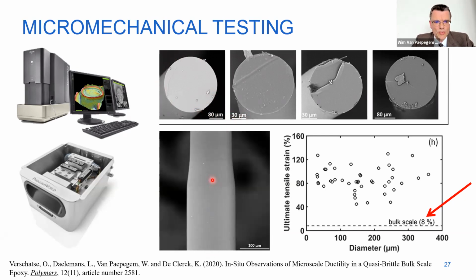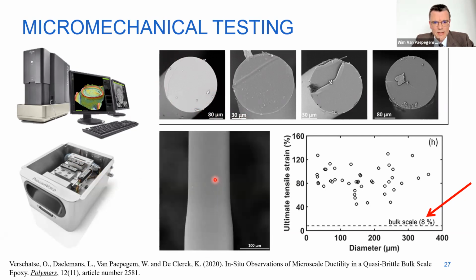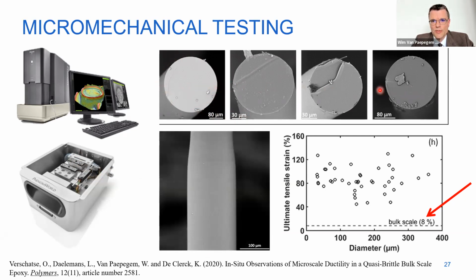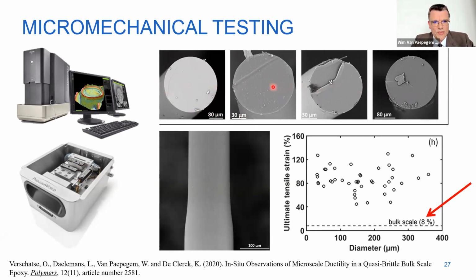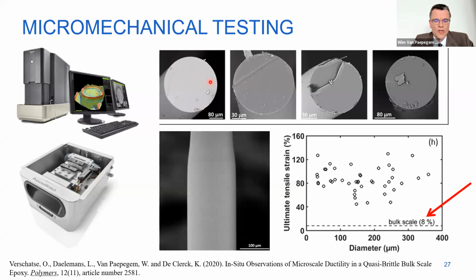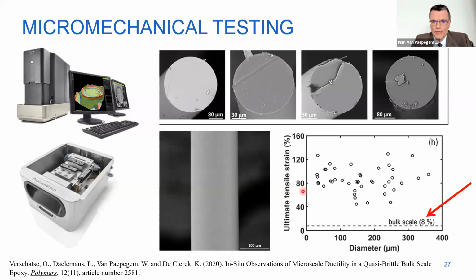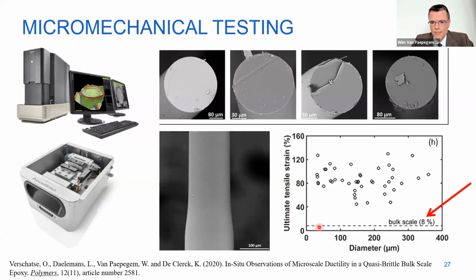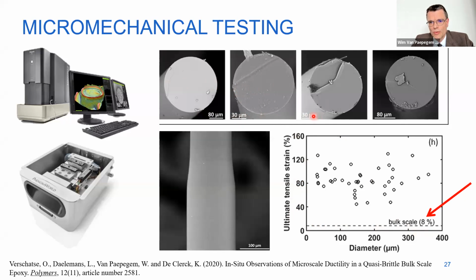And when we test those in an electron microscope in a tensile stage, we see a lot of necking and very ductile behavior. When they are broken, so here you see 4 fracture surfaces, we also don't see any defects. And if we measure this diameter, we even have a correct measurement of the true strain at failure. And when we plot these ultimate tensile strains versus the diameter, because it's not possible to make a very controlled diameter, you have here a scattering diameter.